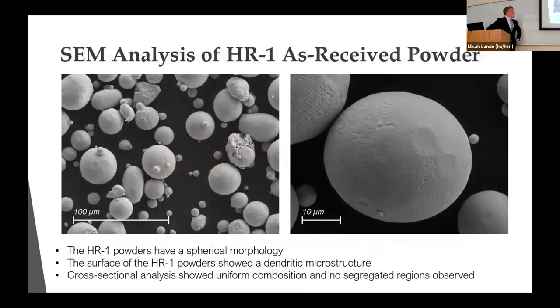So moving on to some electron microscopy. Here we can see our HR1 powder. Again, all the powder particles are roughly spherical in shape, and they're all about the size we expect. We can see on the zoomed in photo here, we're getting the beginnings of a pretty good dendritic structure. And looking at that with EDS, again, these all came out quite homogeneous. There's a pretty good microstructure going on there.